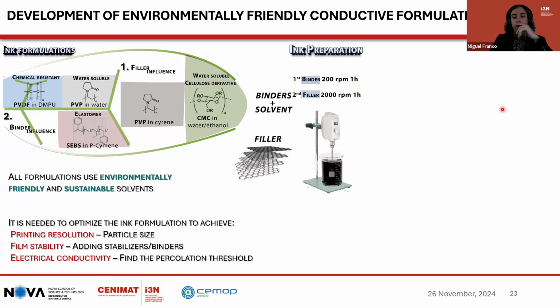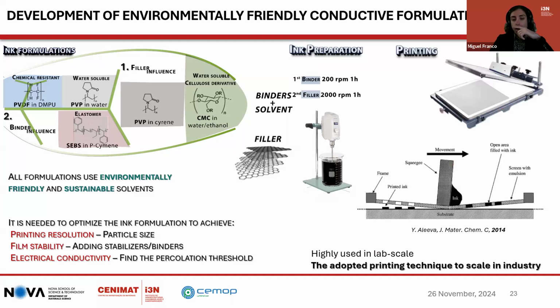The inks were optimized for screen printing techniques, and first the solvent influence was studied using PVP and cyrene. Then the binder influence was studied. In this case, three different types of binders were used: a chemical resistant PVDF in DMPU, an elastomer SEBS in P-Cymene, and PVP in water.